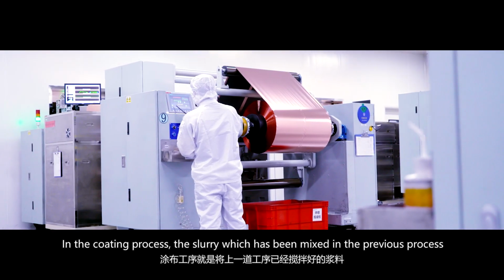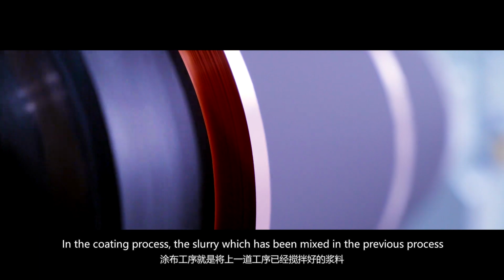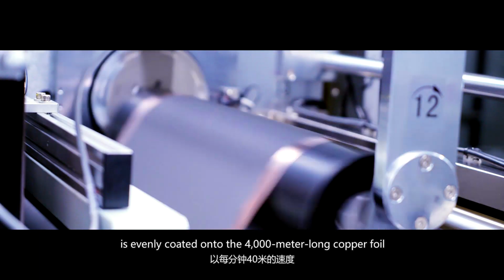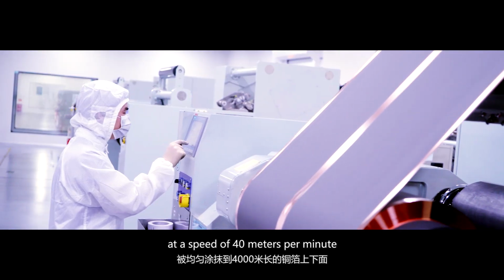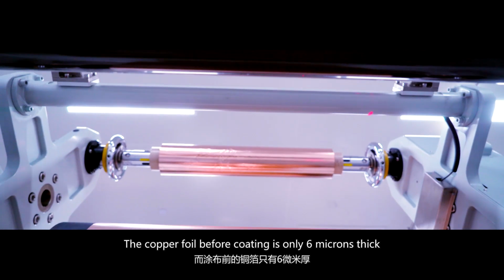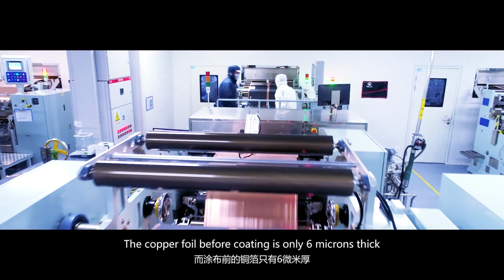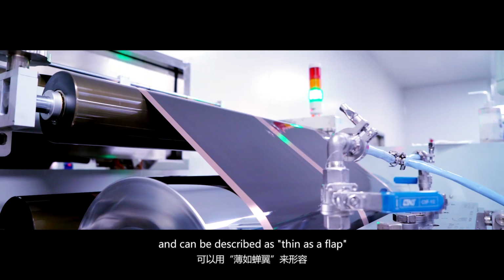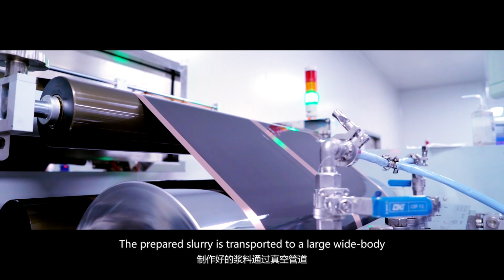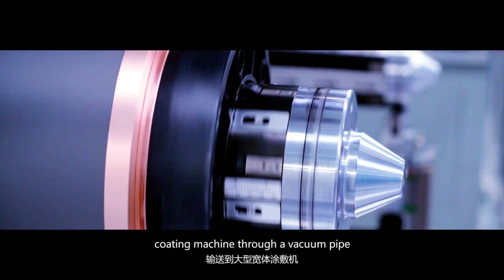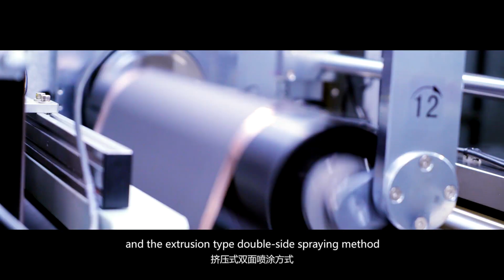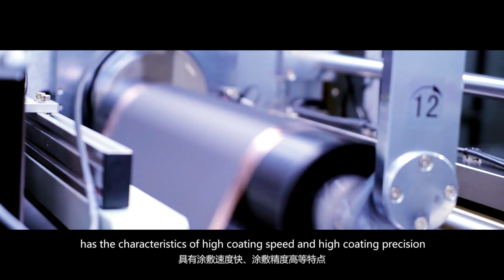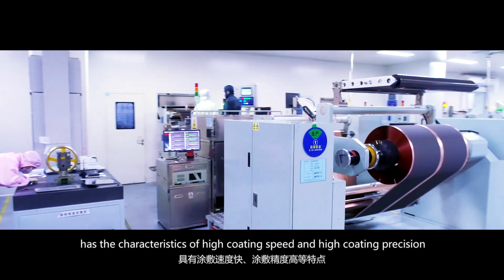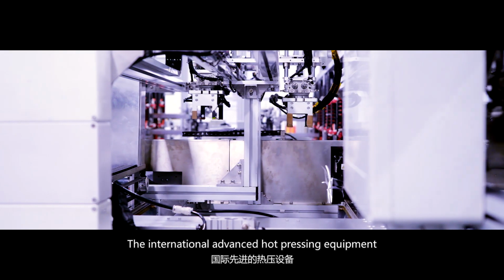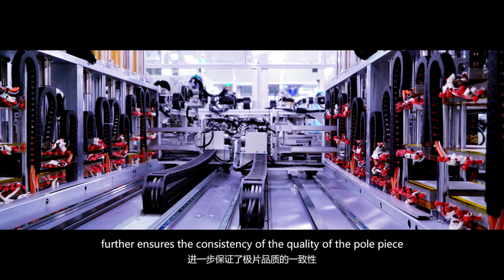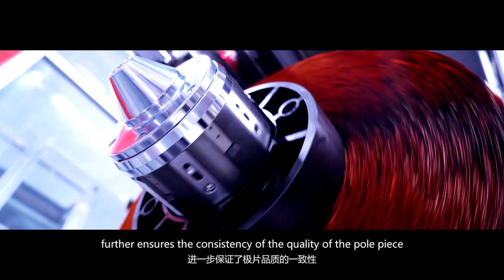In the coating process, the slurry, which has been mixed in the previous process, is evenly coated onto the 4,000-meter-long copper foil at a speed of 40 meters per minute. The copper foil before coating is only 6 microns thick and can be described as thin as a cicada's wing. The prepared slurry is transported to a large wide-body coating machine through a vacuum pipe, and the extrusion-type double-side coating method has the characteristics of high coating speed and high coating precision. The international advanced hot pressing equipment further ensures the consistency of the quality of the pole piece.